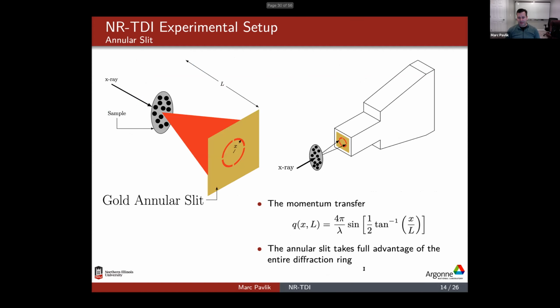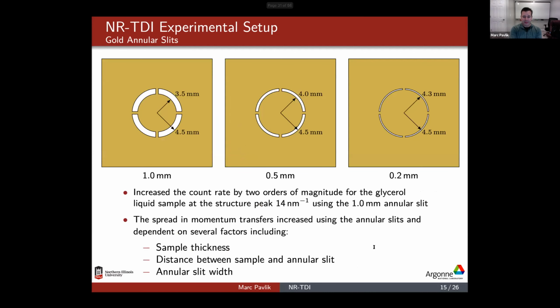So we tried to come up with a different method. We tried adding an annular slit. Using basically the same geometry as before, except now we put this gold annular slit in front of our APD detector, which allows us to collect the entire diffraction ring instead of just a small portion of it. We made three different slits. Using the 1 millimeter annular slit, we increased the counting rate by 2 orders of magnitude, which allowed us to do a full range of temperature measurements in a short amount of time.